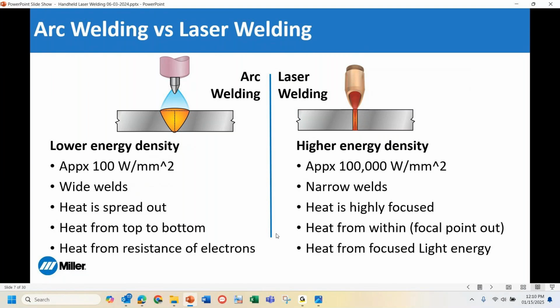And because it's a transfer of electrons, we actually heat the material from the surface, and the heat soaks down into the material because of that resistance to the electron flow caused by the material itself. When we look at the laser welding process, we're about 1,000 times the energy density.